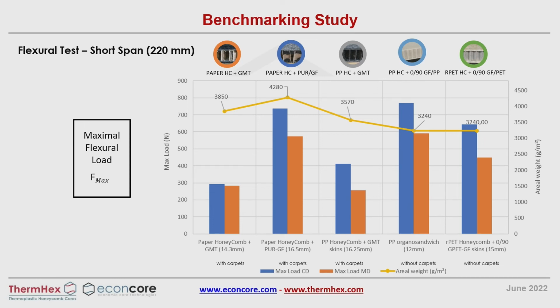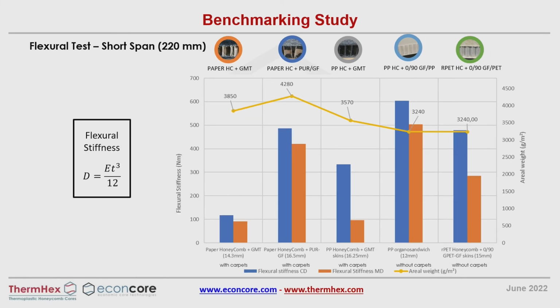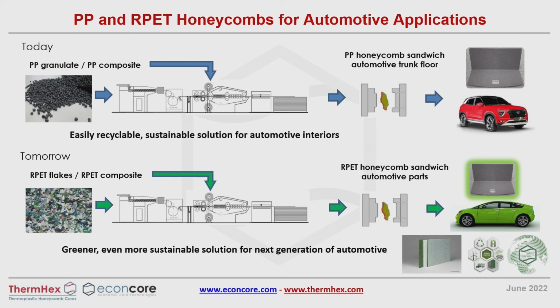And the paper honeycombs with polyurethane is column number 2. Those can be replaced with a glass fiber polypropylene UD tape sandwich, which is in column number 4. And in 5, you see the last one is a recycled PET-based honeycomb with PET glass fiber skins. So this was the maximum force, and this is bending stiffness. There you see also with a complete UD fiber, we can compete and can outperform the polyurethane paper honeycomb. And there was already recycled PET in one of the panels as a comparison.